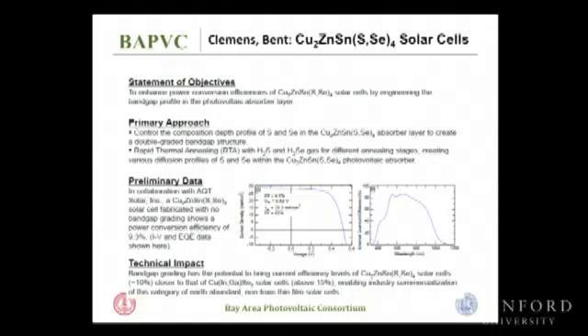This consists of earth abundant materials. It can be low cost in the future. So in Bruce Clemens' group together with Stacey Bent, they already demonstrated pretty interesting efficiency, 9.3% efficiency using a graded band gap idea. They try to tune the materials by controlling the deposition. We also see this type of approach already demonstrates reasonable efficiency. If some resources can be allocated into this project to increase the efficiency further, let's say 15%, this can become very interesting for industry to take over to further develop.